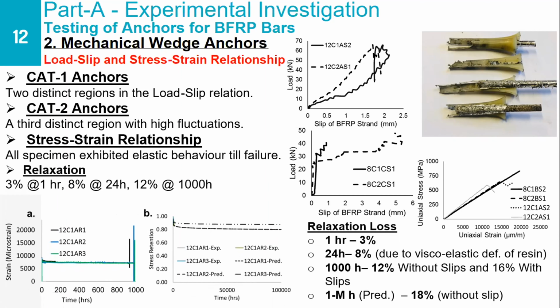We also performed the relaxation test on these BFRP bars, and we can see that at 1 hour, the relaxation loss obtained was 3%. At 24 hours, it was 8%, and it gradually reduced. The rate of relaxation reduced, and around 1,000 hours, it was around 12%. Based on this result, the 1 million hour relaxation loss has been extrapolated to be 18% without any slip of the anchor. So this is the variation of the strain in the bars with time.